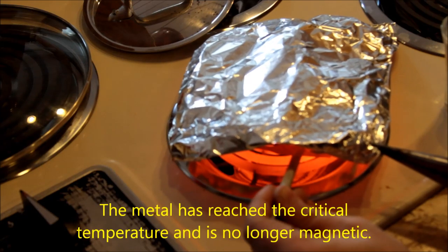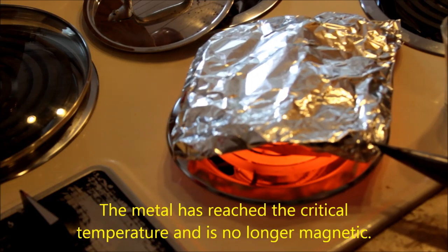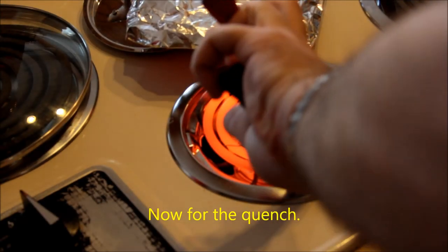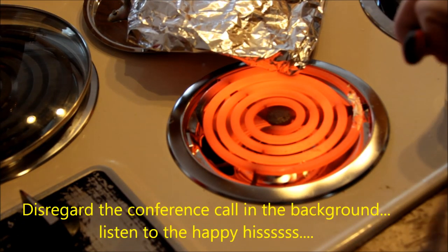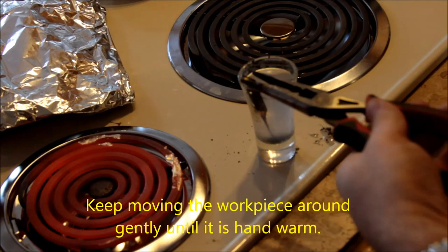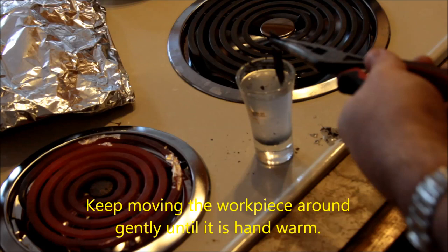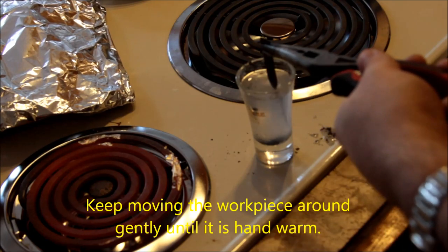Here we have the metal heated up to non-magnetic, so I know that it's hot enough and I'm going to dunk it into my quenching solution which will make some hissing noises. Keep the metal moving to evenly cool it.